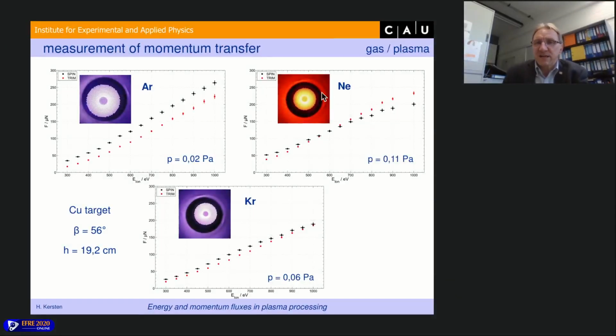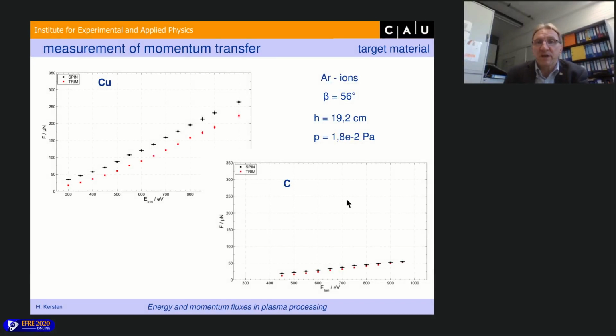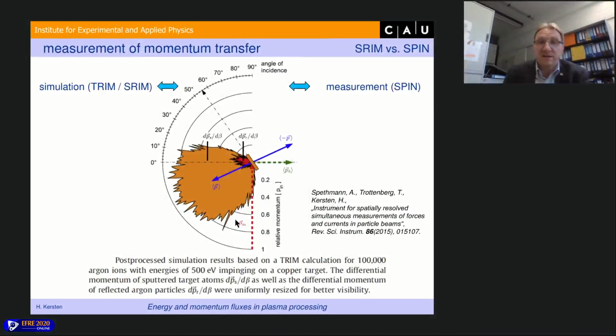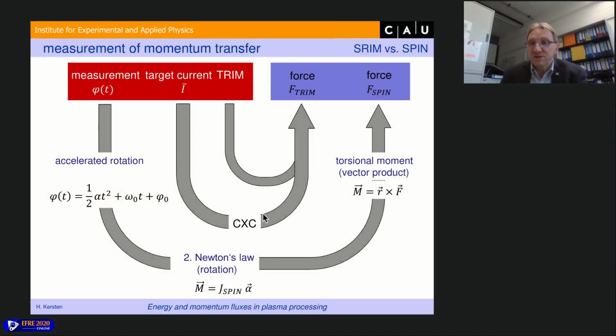So we can do that for different gases, for argon, neon, krypton ions, and for different target materials, for instance, for copper and for graphite. And the force is much lower for graphite than for copper. And of course, the sputtering yield for argon ions is much lower for a graphite target than for a copper target. That you can really see in this rotation, and you can measure that. And by comparing this, you can get information about the sputtering plume and the reflection plume of the particles coming from the target. And now I come to the last example.